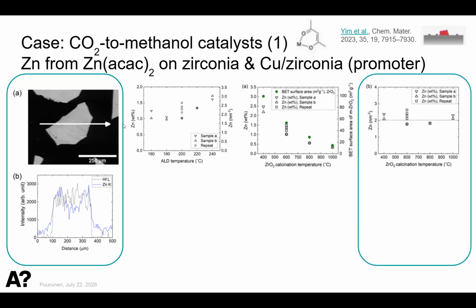For the same samples there are always at least two samples, same processing batch, and we get roughly 2 zinc atoms per square nanometer in all cases. When the temperature goes up, we start to get a little bit more, but otherwise this is really flat. And then the question about tuning the properties of the support. We have also calcined the zirconia at different temperatures, and we see that the zinc loading drastically goes down with temperature, but so does the surface area, the green points here. If you then look at the amount of zinc per unit area, per square nanometer, again in all cases we have roughly 2. So irrespective of the ALD temperature within a small temperature window and the surface area, we get 2 per square nanometer.